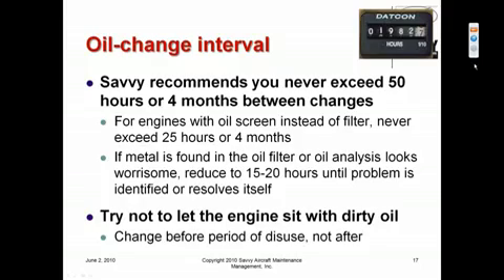If you have an engine that only has a metal oil screen rather than a pleated disposable filter, then you shouldn't exceed 25 hours or 4 months, because the screen does not do nearly as good a job of filtering particulate material out of the oil, and therefore the oil has a much heavier load of particulates that it has to keep in suspension so that you don't wind up getting a bunch of sludge in the engine.